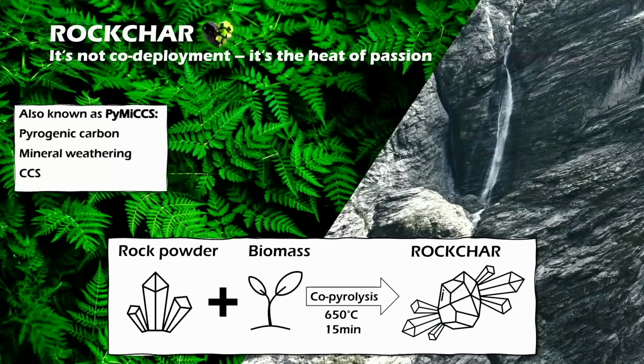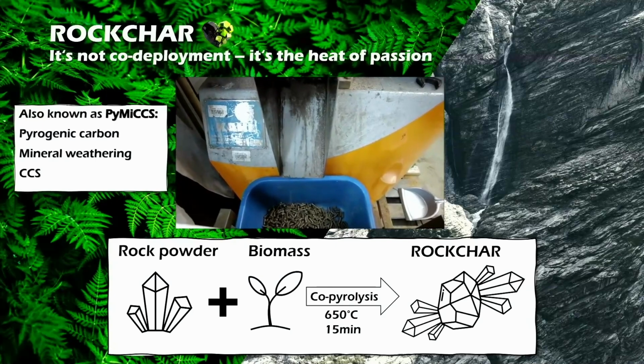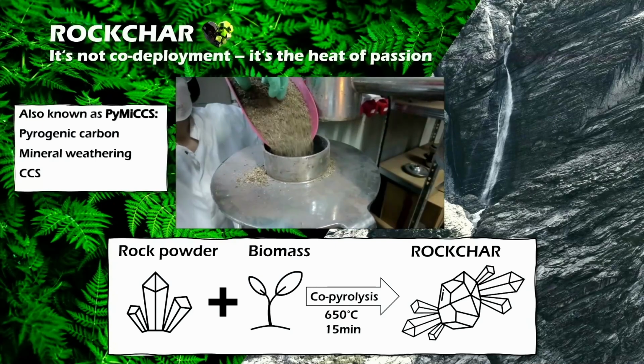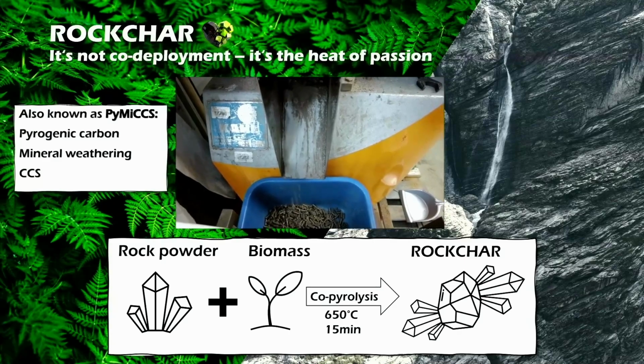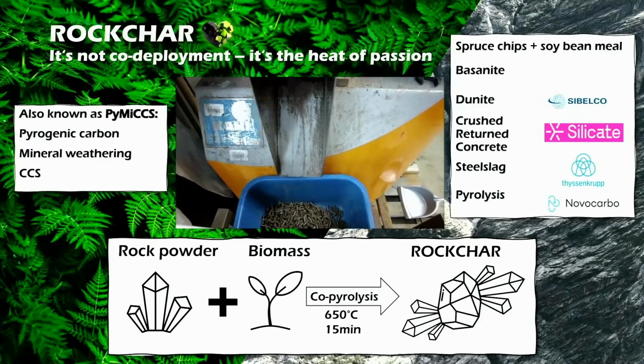And what I do is I mix rock powder with biomass, and then I co-pyrolyze both together at 650 degrees for 15 minutes, and what comes out is ROCKCHAR. To make sure that minerals and biomass can interact with each other during pyrolysis, I have to pelletize them. And this is also very convenient because when I spread it on the field, I have less dust production. Normally, especially when you deploy rock powder, you have these huge clouds of dust, which doesn't make you a famous person around that area.